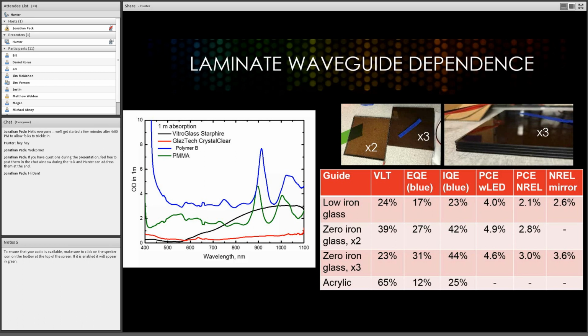And then as you go towards better quality glass, iron itself has an absorption band in the IR. But as you get to higher quality and essentially remove the iron, that goes away. You can think of quartz or optical quality glass that you might use for cuvettes. And anyway, on the bottom right is the summary of how those perform. I'm sorry, there are several different effects being convolved there. Long story short, the lowest iron or zero iron performs best, much better than acrylic and better than low iron. And these numbers for our EQE and IQE, those actually aren't published, so you guys are seeing these for the first time.